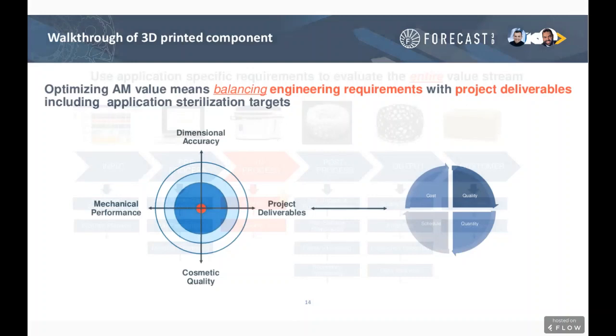So for this particular case, we're pulling from an HP study, evaluating PA12, their standard nylon material, and evaluating the mechanical performance, the visual performance, and the dimensional accuracy of the components, going through a variety of different sterilization methods. So this graph is essentially indicating that some tensile bars were created and printed in a standard fashion, and then tested as a baseline. From there were different test methods or sterilization methods, one being autoclave at 121C, one being autoclave at 134C. Then formaldehyde was a chemical treatment option. It was supposed to be a similar treatment to the ethylene oxide.